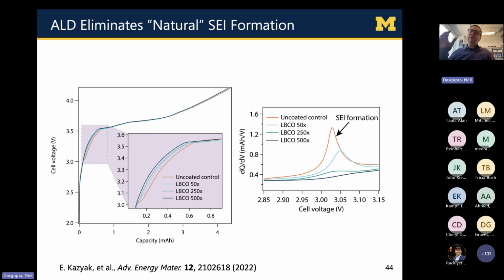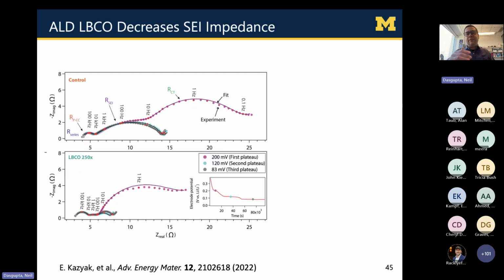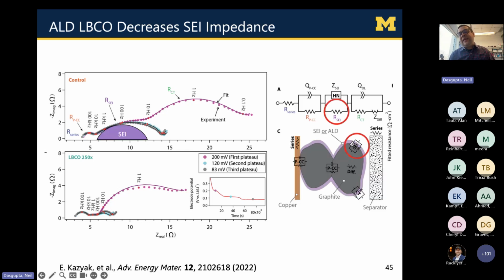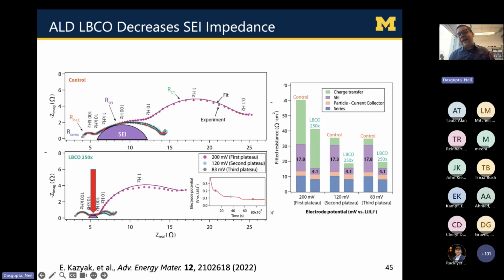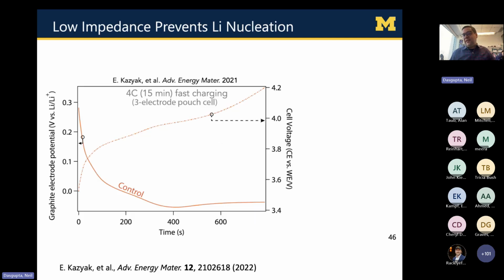We were amazed to see that when we coated this ALD coating on the graphite, we were able to eliminate the SEI formation during the first formation cycle of the battery. Again, a lot of data here, and I'm a little short on time, so I'll go a little quick here. But long story short, the impedance of the interface becomes dramatically lower when you coat this ALD coating onto the surface of the graphite compared to the natural SEI, we call it, that forms from the decomposition of the electrolyte.